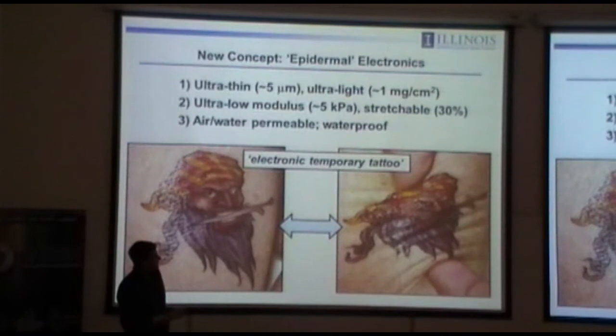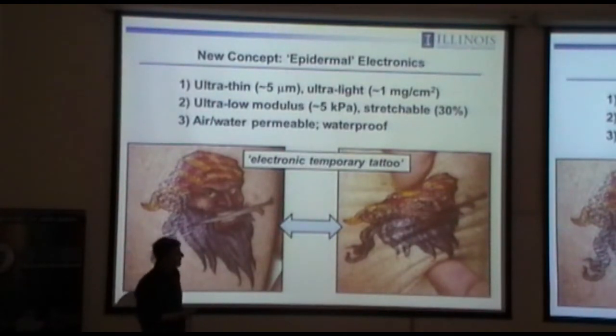It turns out that the skin can not only fold and bend and wrinkle, but it also stretches. It doesn't stretch by a lot. It's not like a rubber band, but it can stretch about 30% before it starts to tear. And so if you want to match the mechanical properties of the skin, it not only needs to have a low modulus, but an elastic response up to at least 30% strain, maybe beyond.